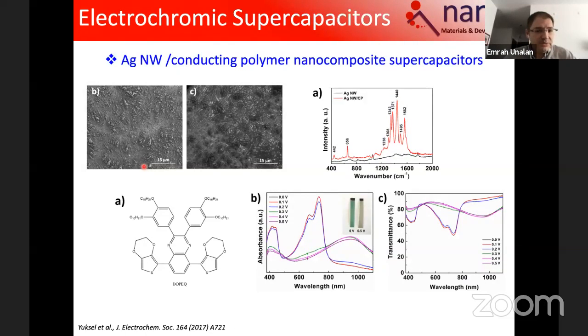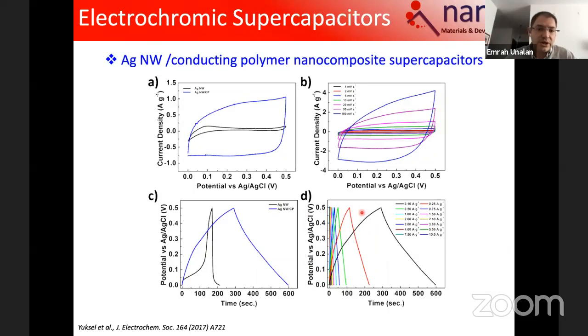So with the colleagues in the chemistry department, they have these very different fancy polymers that are solution processable. So on top of the silver nanowires, we can spray coat these polymers. And these polymers are, as you see in the ground state, in the reduced state, or if you wish, it is very bright green, as you see over here. And then when you charge it or you oxidize it to 0.5 volts, why 0.5? Because we had to stop there for unprotected silver nanowires, as I told you earlier on. When you put it to the oxidized state, it is becoming completely transparent. So this color change can also indicate the state of the charge.